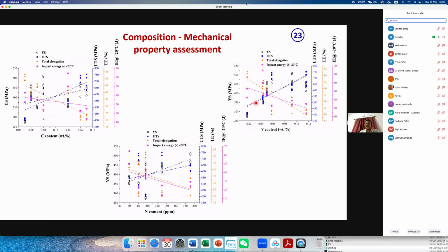Vanadium, strength, it's more or less similar effect. It increases YS and UTS both in the same way. It's showing a little bit of detrimental effect more on elongation. Nitrogen, it has stronger effect on yield strength based on the data readings, whatever we have produced under this project, and same kind of a slight negative effect on these two. But the great thing is, with such a low carbon level, we have met such a high property requirement.